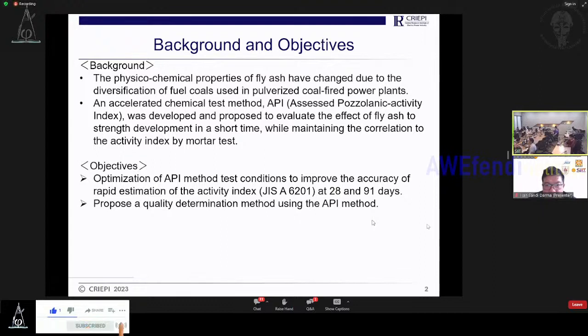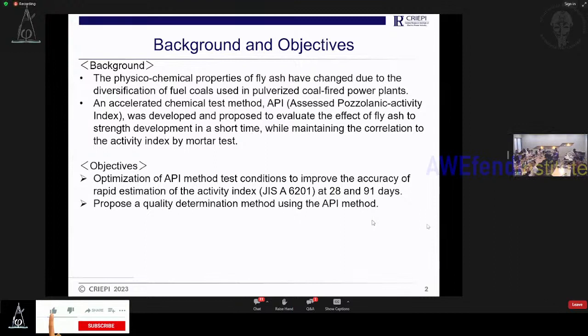The background of this API method is like this. The physical and chemical properties of fly ash have changed due to the diversification of fuel coals. In Japan, we import a large amount of coal from many countries, so the character of the fly ash can easily change. And we need a rapid estimation method to obtain the properties, especially the strength development of the fly ash. Now we apply the mortar test, and it takes about 1 to 3 months to obtain the result. So we need to shorten the testing period.